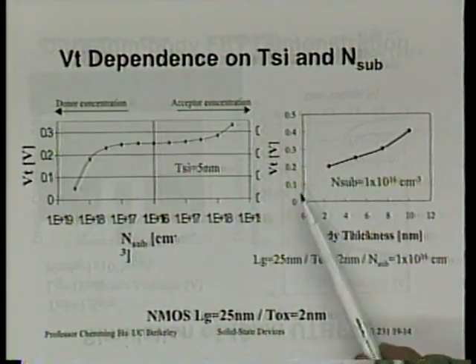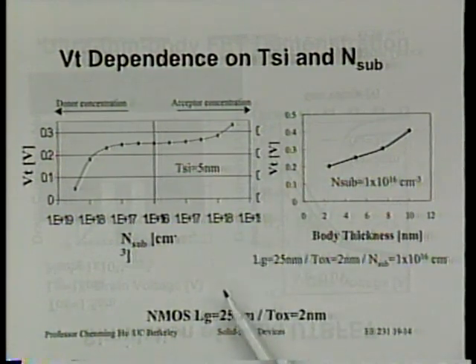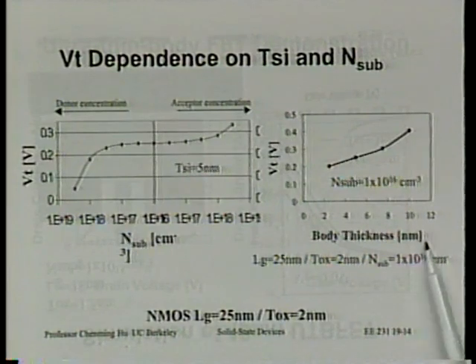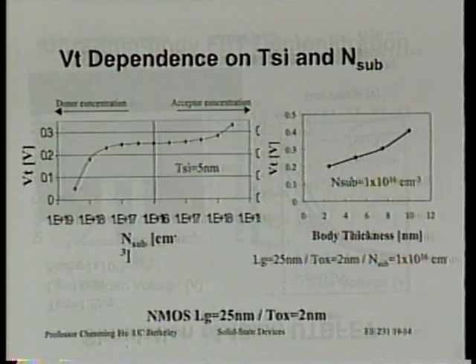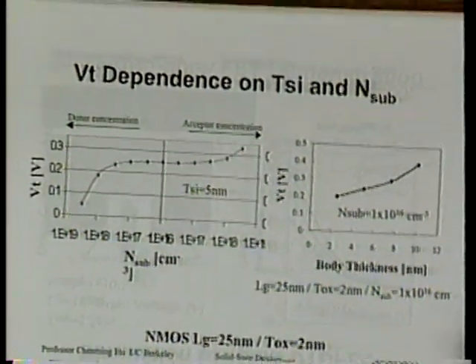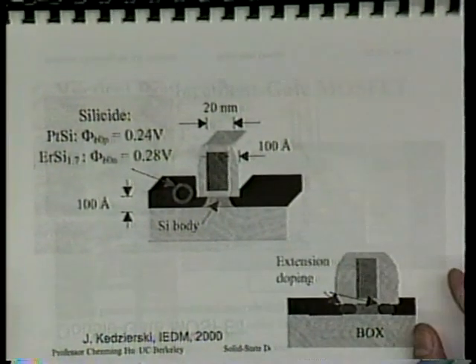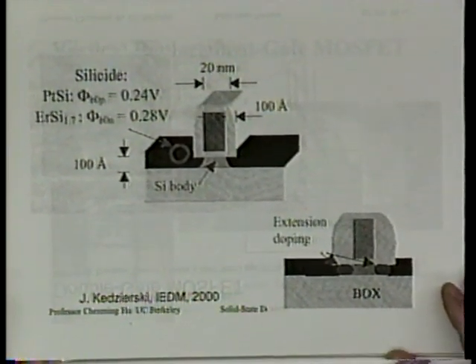The other one is that we also noticed VT now, however, can be sensitive to body thickness, even though the doping concentration is not very large. And we think it has to do with quantum effect, actually. And this is something that Day Won and Yang-Q recently just finished modeling using quantum mechanics. You see, when the silicon film is so thin, we're now really talking about a quantum well. And as a result of the quantum well, the energy state rises. If the energy state rises, the amount of band bending required for the surface to be inverted will be different. And this will have an impact on VT. So this is another problem when the film is thin, something we have to deal with in planning, in dealing with the process variation.